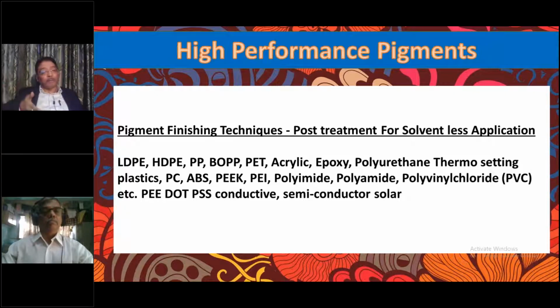In order to get one-third depth, you require 0.001 pigment, and at that level you have low MFI, LDPE or HDPE, and these don't have any polarity. They will not disperse the pigment, and it would be a forced cohabitation of the pigment in a master batch.